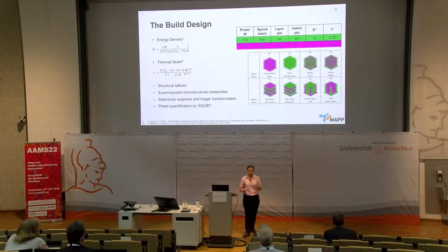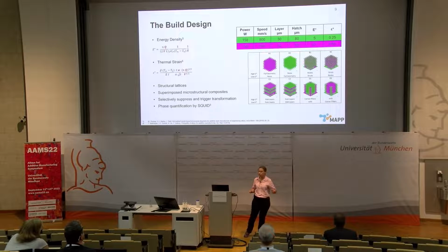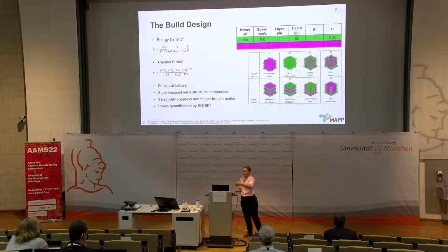We've then taken those two parameter sets and applied them to structural lattices. So these have been basically just superimposed as composite structures on top of what's already a structural lattice geometry. The lattice geometry we've used is a diamond cubic structure. It's fairly common in the literature to start with diamond cubic and move on from there, so I'm sure you're aware of that as a structure. But what we're looking at here is applying that composite approach. So kind of the Lego bricks from earlier, but applied in a different way.